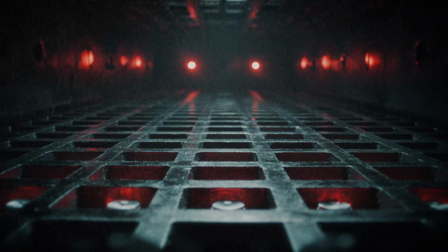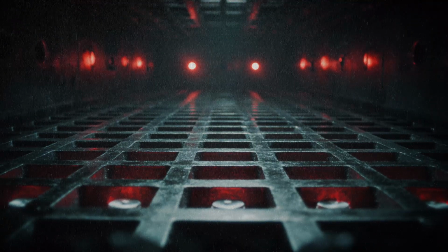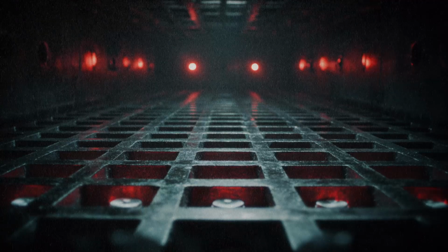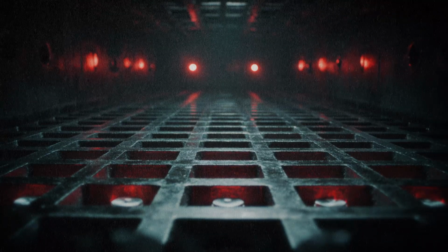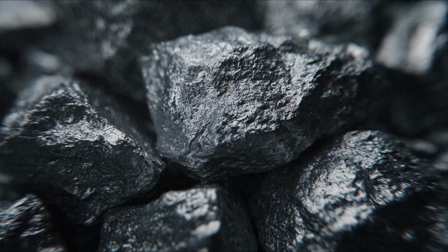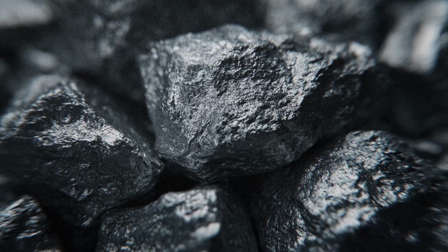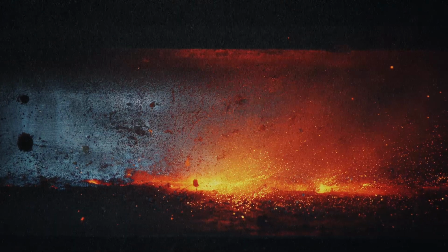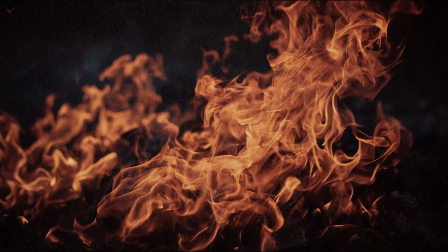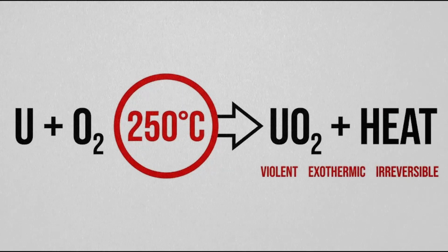The fuel inside Windscale's core was natural uranium metal, 72,000 cartridges of it, threaded through the graphite. And uranium has a property that most people never consider. It burns. Expose metallic uranium to oxygen at temperatures above 250 degrees Celsius, and it oxidizes. Violently, exothermically, and once started, almost impossible to stop.